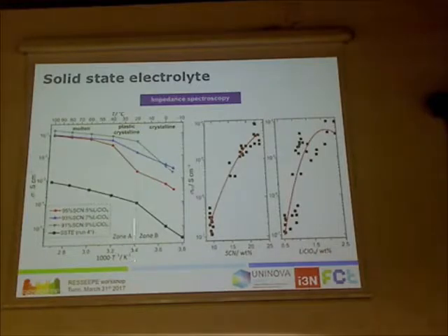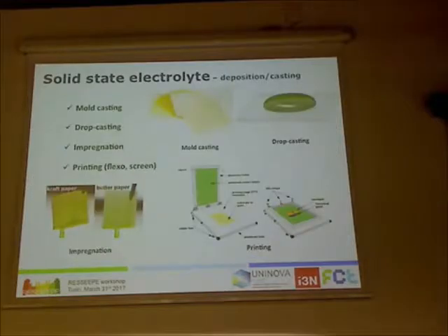Just to show the ionic conductivity that can be reached with this thermosetting polymer. Of course it's much lower than gel or liquid electrolytes. And we also need to consider that if you put too much of this plastic crystal, this molecule I told you before,